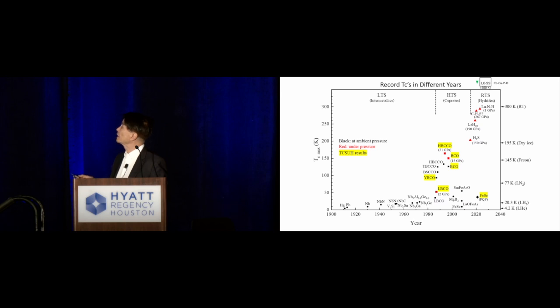Now if I plot the superconducting temperature record as a function of time, you can see this plot. Originally when it was discovered, it was 4.2 degrees, and then later on continued to increase. And then when we came into the field with the cuprates, we raised the transition temperature from 4.2 degrees all the way up to 164 degrees Kelvin here. I should mention all these highlighted in yellow were done at the University of Houston. But then recently, when people looked at the hydrides, the Tc goes even higher, at least they claim to be higher, even up to room temperature, as you can see shown here. And even in one case without pressure, it can go up to 300 degrees Kelvin. And that's really a room temperature superconductor, if it is true, okay?